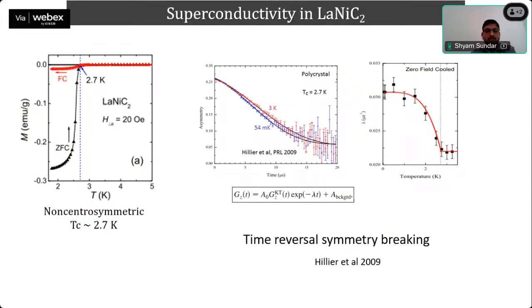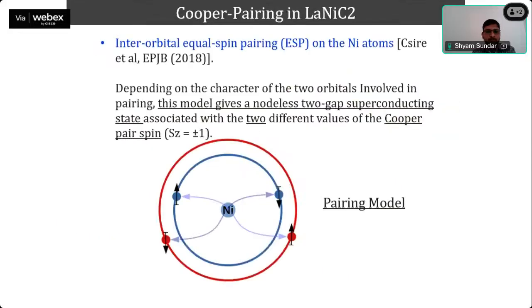So then it was important to understand what the gap structure and the pairing symmetry in this superconductor look like. For that, people did some theoretical calculations and saw that it can only happen when there is an interorbital equal-spin pairing on the nickel atoms in these materials. Then it can show this kind of spontaneous magnetization at TC. And in this model, depending on the character of the two orbitals involved of this nickel atom,